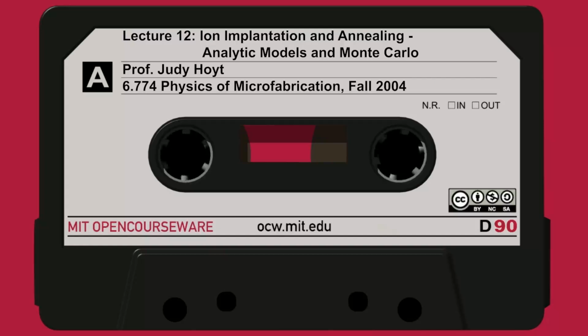Remember when we talked about SIMS, we talked about a knock-on process. So SIMS itself will tend to produce tails, just from the secondary ion mass spectrometer, just from the analytical technique I used. So you have to be sure that somebody wasn't actually modeling an experimental artifact. So you have to take anything based on tables with a grain of salt, and just be a little careful to check it out.